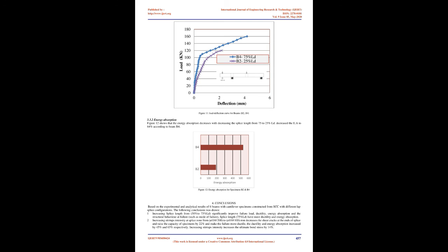3.3 Influence of lap length in SCC beams. 3.3.1 Load capacity. The recorded ultimate load of beam B2 was about 80% of B4. This can be attributed to the fact that increasing splice length led to increasing the failure load. The smaller ductility of B2 compared with that of beam B4 is due to the smaller ultimate load of B2. Beam B2 had lower deflection than beam B4, which indicates that a splice of 75% LD enables the beam to behave in a more ductile manner and improves the moment capacity.